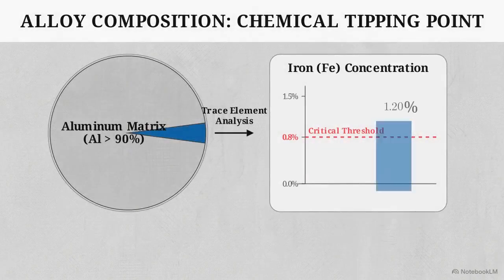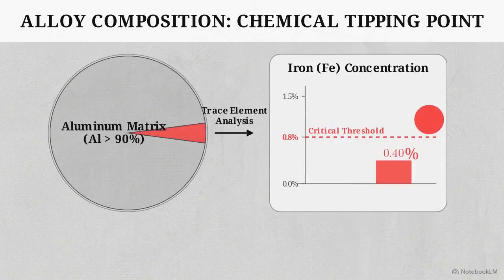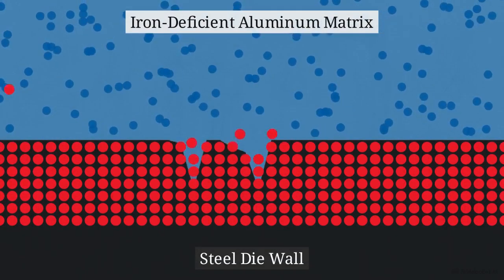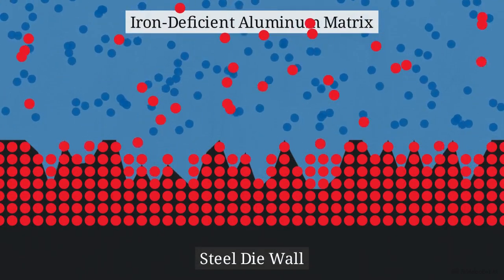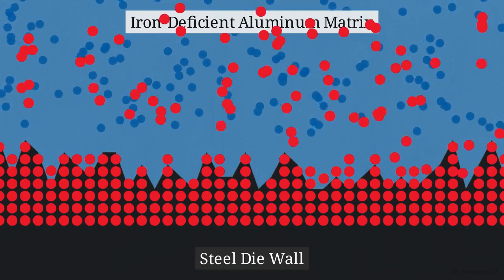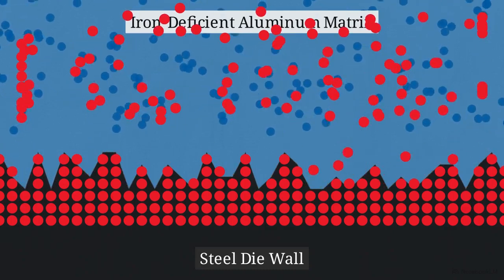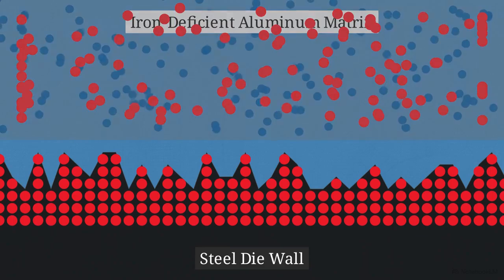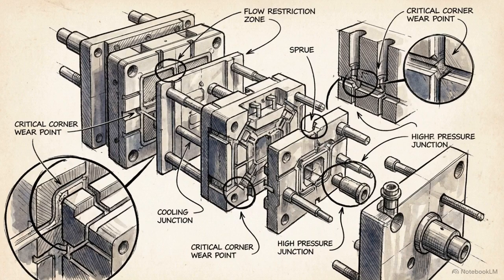Beyond temperature and pressure, the composition of the injected aluminum alloy itself acts as a hidden trigger for the defect. The problem often accelerates when manufacturers utilize an aluminum alloy with an exceptionally low iron content. This sets up a dynamic of elemental stealing. The iron-starved liquid aluminum actively extracts and pulls iron atoms directly out of the adjacent steel die wall to chemically stabilize itself. Mechanical design flaws in the mold will compound this chemical theft.